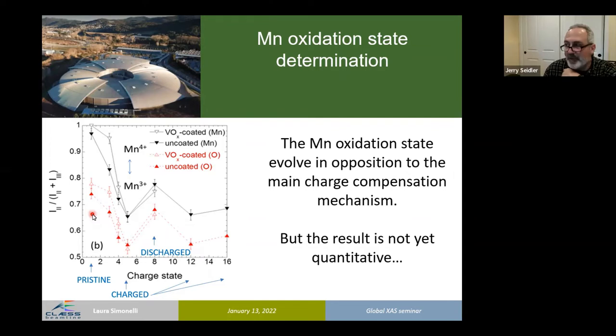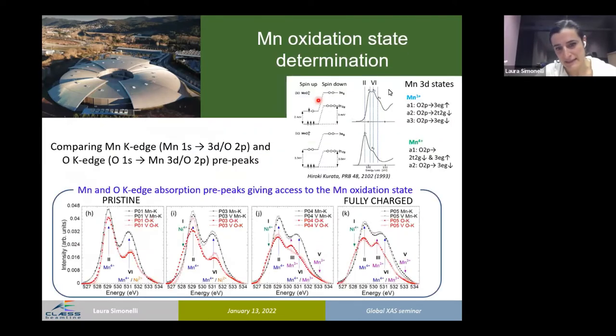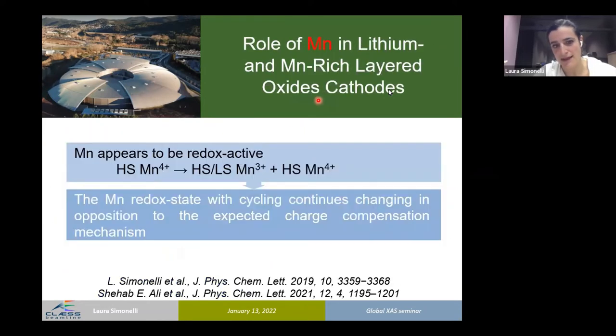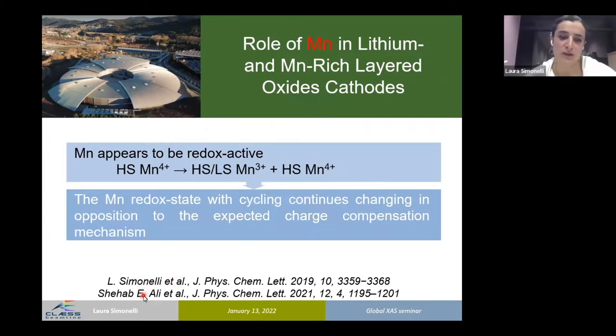A question from Yulia Pushkar from Purdue asks whether the results shown are published. Yes, the references are noted at the beginning of each section. The results are mixed across publications for easier understanding. A comment is offered: working on the oxygen evolving complex with manganese 4+ and 3+, seeing manganese 3+ during oxidation raises the possibility of peroxide formation. The speaker responds: comparing oxygen K-edge with manganese K-edge, which cannot see peroxide, and finding one-to-one correlation, confirms at least a strong manganese 3+ contribution. Regarding manganese 3+ low-spin configuration — which is unusual — there are calculations predicting it, specifically a 2007 prediction by Wang, estimating a rhombohedral phase that should favor reversible cycling.